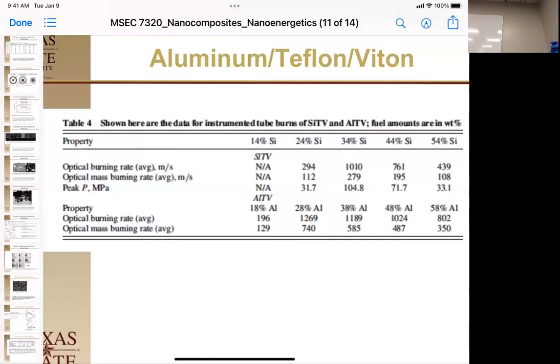So it turns out that 34% actually is the burn. Actually, if you do the calculation, the fluorine to silicon mass ratio is really good right there. You have just a little bit of excess fluorine. But if you look at the burn rates of the aluminum here, with a very little amount here, you saw very little burning. You saw much faster burn rates across the board. But again, this mixture, somewhere right around 30%, these are the two best, there we get the best performance. And again, it's balancing the amount of oxidizer you have available to the amount of metal you have burning.